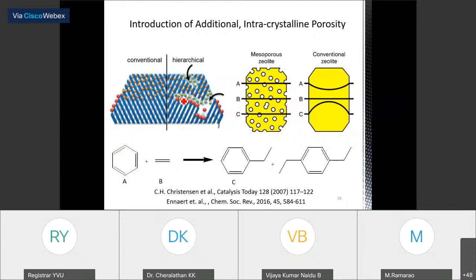And in the case of additional porosity introduced into the crystal, what will happen? Not only are the smaller molecules diffusing fast, at the same time the bulky molecules can go and react with the active sites. It was made possible by the introduction of these mesopores as well as macropores. Ultimately, what will happen when you introduce this kind of additional pores? The difference in the concentration gradient.